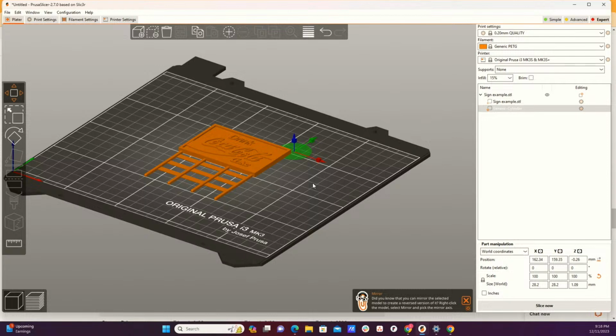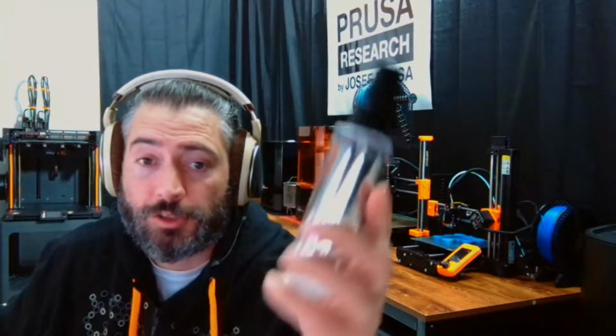So if that's what he was talking about, the brim, if it solves your problem, you want to use it, and then you adapt post-processing to help fix whatever you didn't like about pulling the brim off, like discoloration. Like I said, a heat gun or a little mini lighter torch. You brush that really quickly, back and forth, left and right over the discolored area, and it should regain its color. Otherwise, you learn other little techniques to shore up the part that's struggling. And then one last thing you could do if you're having trouble with your prints is, let me see if I can get back here, spray adhesive.